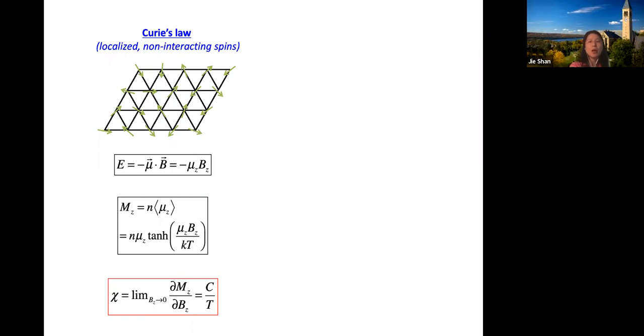Before I explain the experiment, I would first like to remind you of the basic idea behind the magnetic susceptibility measurement. For localized non-interacting spins, it's described by Curie's law. If you apply a magnetic field, you polarize those localized spins. The energy can be described by the product of the two, and you can find a magnetization at a finite temperature, and find the susceptibility as the ratio of the two in the limit when the magnetic field goes to 0. For localized non-interacting spins, we know that susceptibility goes like 1/T.